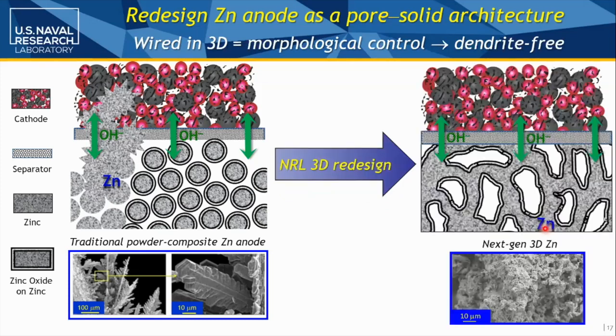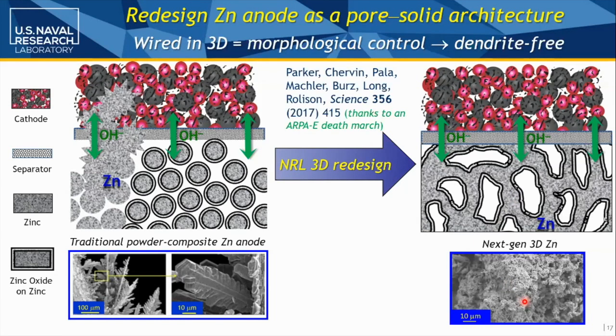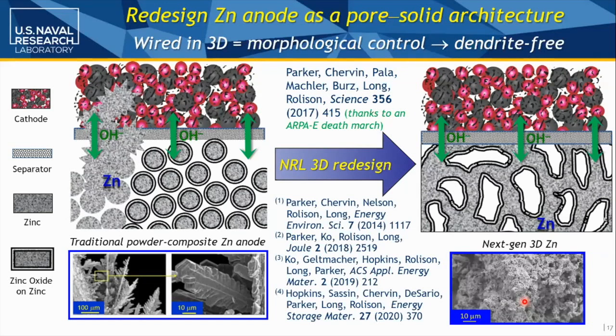So if you think in 3D, you're going to take that powder and now fuse it into a sponge. So here's the cross section of the sponge. And now the zinc oxide is only going on the walls, and you've always got a good metallic internal core that allows you to talk back to your macro scale current collector without any problems. So in our case, the sponge goes in, sponge comes out. And no big surprise, we've had lots of papers on that, and as you'll see, some patents.